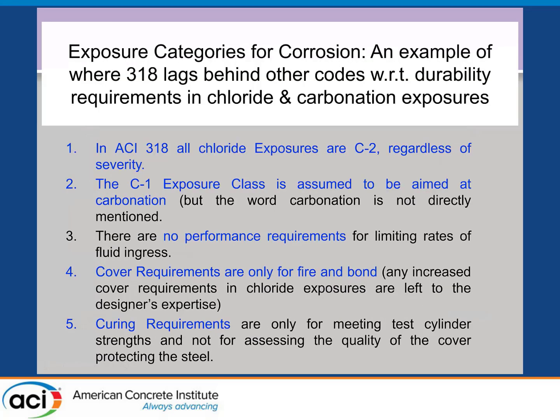And one of the issues, as I mentioned, the only exposure class for chlorides in ACI 318 is C2. Doesn't matter how severe it is or what the cause of the corrosion is, whether it's marine corrosion, de-icing salts, or saline soils, it's all C2. The C1 exposure, which is the only other corrosion class in 318, is just wet environments without chlorides. And the only thing I can think of is that this is assumed to be related to carbonation corrosion, but they don't mention carbonation anywhere. And there's no performance requirements, as I mentioned, for limiting the rates of chloride ingress.